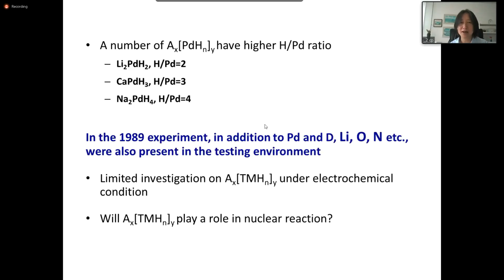And I also like to highlight the most important thing I want to deliver: palladium hydride is of focal interest in nuclear fusion, and as mentioned before, people are looking at the hydrogen to palladium ratio being as high as possible. For complex palladium hydrides, the hydrogen to palladium ratio could be as high as 4. Of course, that's a very different hydrogen state as compared with neat palladium hydride. But this is something very different, because we have lithium, calcium, and sodium here. We can stabilize these complexes.